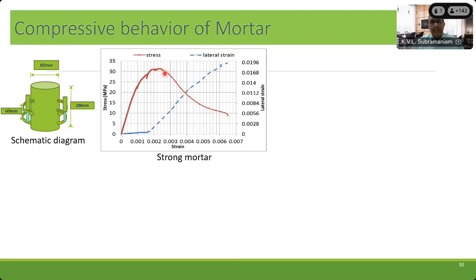And then the residual stress, or the stress resistance, slowly decreases as I increase the strain. And you see the maximum stress is reached around 0.002. This is exactly what we expect from concrete. It looks like a typical compressive stress-strain response of concrete. What is important is this lateral strain.